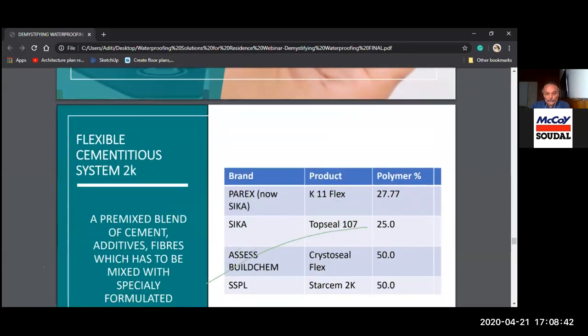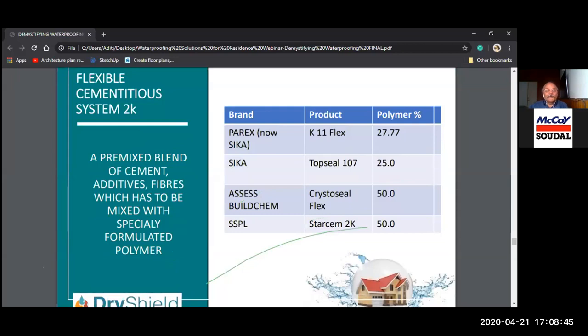So I would give you a small example of 4 different products. There's a good brand, Parex, which has been taken over by Sika now. K11 Flex, I have used more than 100 tons in the last few years. The polymer content is 27.77%. Sika has a very popular product called Top Seal 107, which is specified in many government tenders. It has a polymer content of 25%. And believe me, it's a very expensive product, but its polymer content is among the lowest.